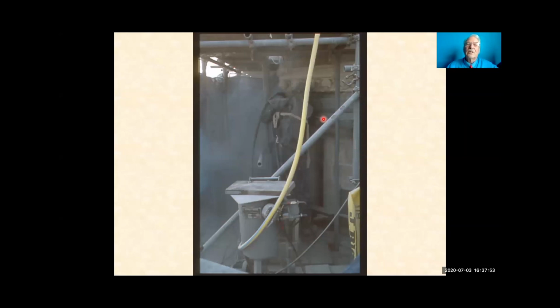This is blast cleaning. Well, I showed you a photograph of this the other day. This is the band around the outside of one of the cathedrals here. And of course, it's right against the stonework. So we have to protect the stonework with, in this case, zinc sheeting pushed down the back. But a big problem with this process, whilst it's very fast, is that you can't see what you're doing. So it's not very controllable for various reasons, and that's one of its limitations. You have to be very, very careful using this process on historic metalwork, especially anywhere near a historic building.